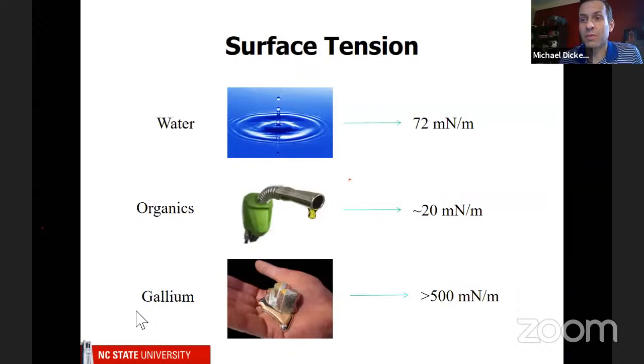Okay, so this is really weird. And one of the reasons it's really weird is that liquid metals have enormous surface tension. If you think about organics, like gasoline, for example, a typical surface tension value would be about 20 to 30 millinewtons per meter. Now, I know when I was an undergraduate, I didn't think about these units. So don't worry about these units. Just look at the numbers. 20. Water, which is very polar, is 72. So that's considered huge. Gallium and other metals are like 500, 700, sometimes 1,000. So really, really large. And this is the largest one at room temperature.